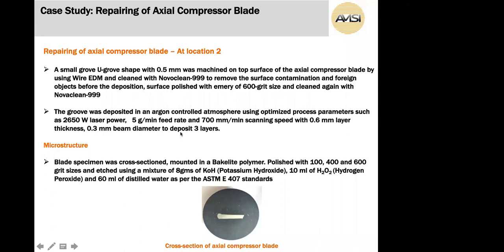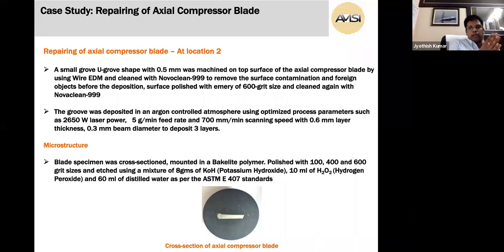Again, we have studied the microstructure of the bonding material on the deposited material at two locations. The initial one was at location 1. Again we sectioned the deposited material with the base material of the axial compressor blade, and we studied the microstructure at location 2, where it shows the complete bonding between the layers. Again, we did all the process of cleaning the surface for microstructure analysis, and all those initial preparations were made as per ASTM standards. Then we studied the cross section of the compressor blade, with clear bonding between the base material and the deposition.